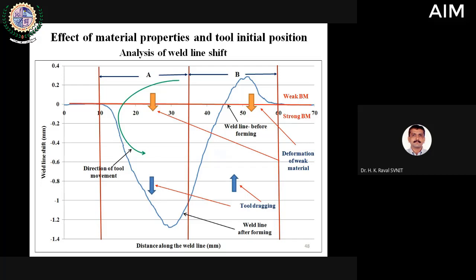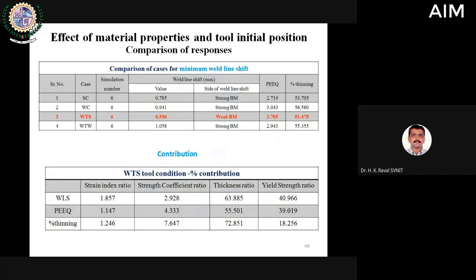So that is one of the key pieces of information we could get when single point incremental forming was conducted on TWB. Then all four cases were compared for the minimum weld line shift, minimum plastic strain, and minimum thinning. And it was observed that the weld-to-strong combination, meaning the tool starting point is on the weld line and moving towards strong, gives rise to minimum weld line shift, minimum plastic strain, and minimum thinning, because thinning should be less. If thinning is higher, more chances of failure.